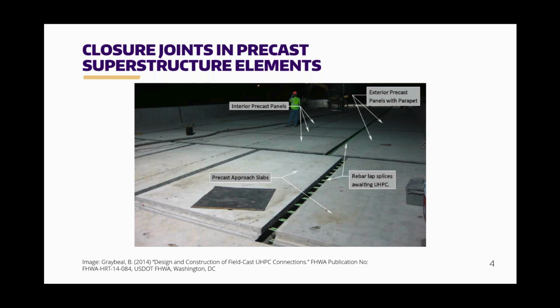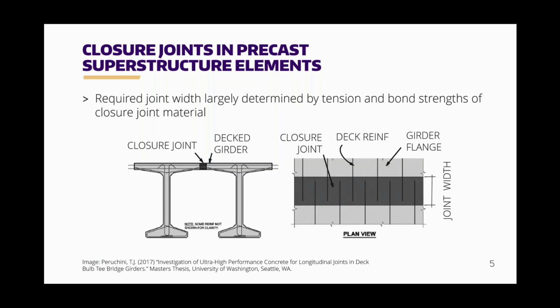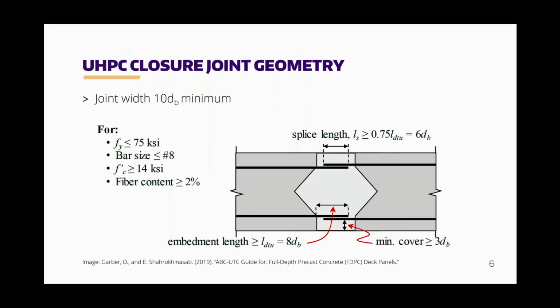And it's not just for deck panels. This could also be an application where you have deck girders. So you have two deck girders, you have a closure joint in between those deck girders as well. And the width of that closure joint is largely determined by the tension and bond strength of the closure joint material. So you can see you have those protruding reinforcement from one element to the other, and those need to be spliced in our joint. And that's going to happen through a non-contact lap splice. And UHPC is a perfectly good solution for this, and it's a preferred solution presently.